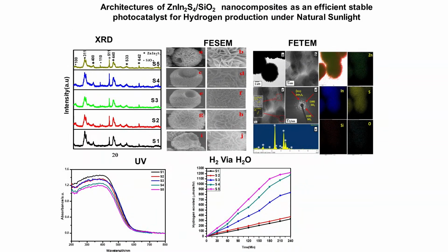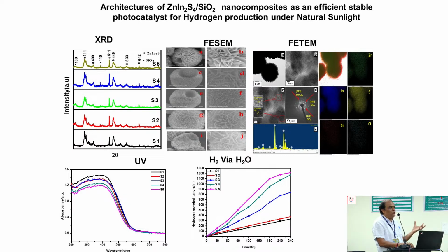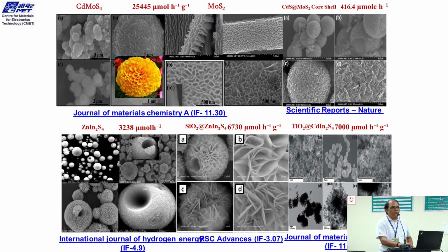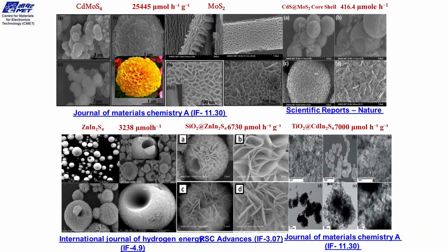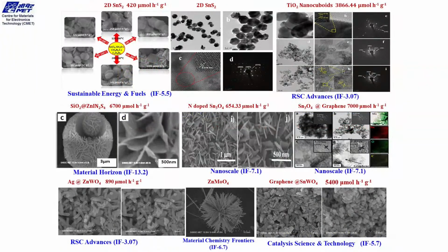Then we tried a combination of two materials to see whether the efficiency of hydrogen production improves, and we found that when we combine two semiconductors together, the electron-hole recombination can be suppressed, and the free electrons will be available for hydrogen production. So these are the many catalysts we have developed for hydrogen production, and we found that some of the catalysts are good for hydrogen evolution, and we can use them in technology. These are all the catalysts we developed in our laboratory. These catalysts can be made on a larger scale, and we can have a bigger reactor system and produce hydrogen in large quantities.